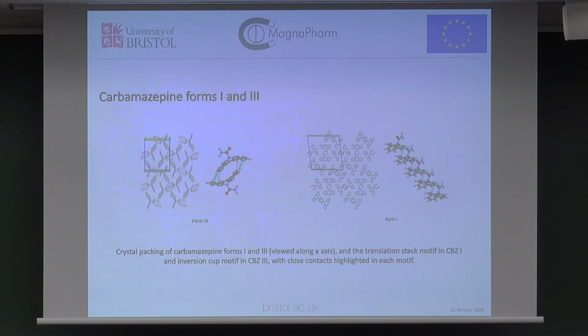This again was work by UCL. Form 3 has this inversion cup motif, which goes through the crystal, and all of the hydrogen bonds point in the same direction, which is kind of interesting. Form 1 has these kind of offset stacks.